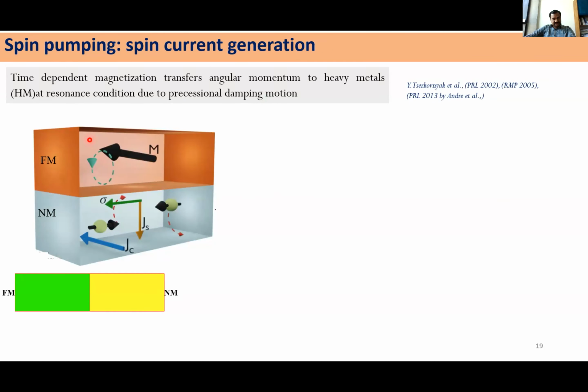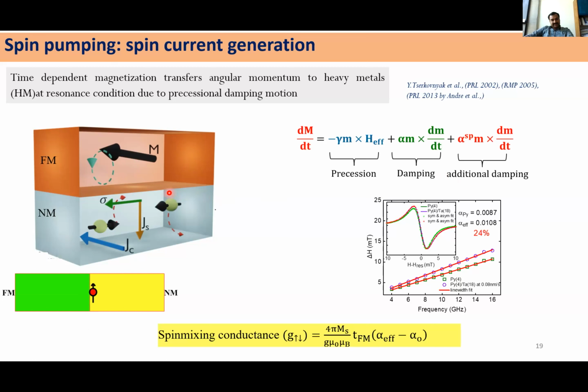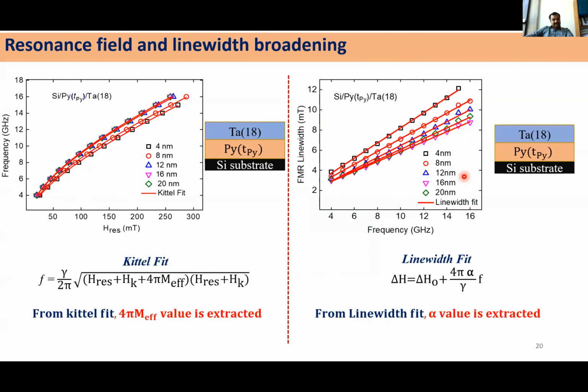Okay, so you have an intrinsic damping, and then due to the larger precession, because of the loss of spin angular momentum, that can be seen as an additional damping. That helps us to find out the spin mixing conductance, which I will talk about later. So from the ferromagnetic resonance technique, we found the frequency as a function of H resonance. We found 4 pi M effective from the Kittel fit, and the damping parameters were found from the line